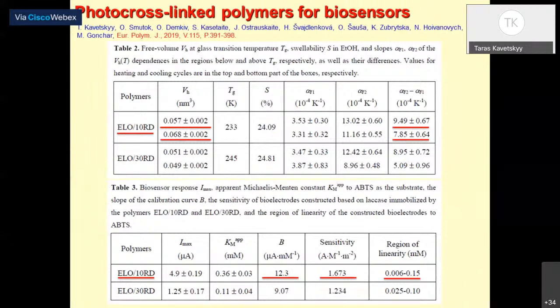So when we compare these polymers with PALS results and the biosensor results, we found that for this ELO/10RD, we have again the largest changes in microscopic free volume below and above Tg. Again, we have for these biosensors the largest sensitivity and even a larger range of linearity. So again, a correlation: when we have larger changes in microscopic free volume, we have the larger sensitivity of biosensors.